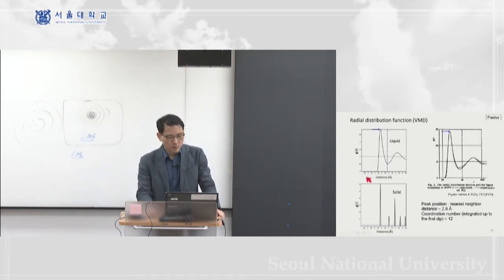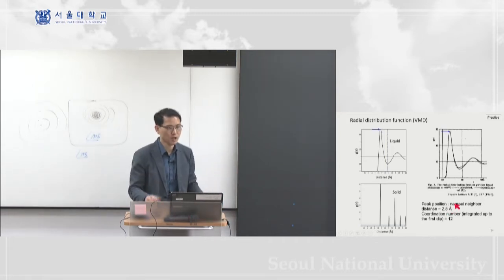All right, so the peak position here occurs at 2.8 angstrom. So therefore, this should correspond to the average nearest neighbor distance of the liquid.